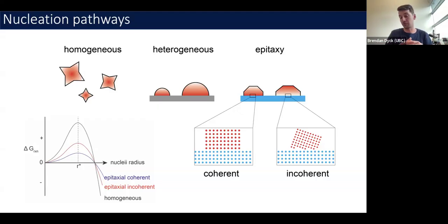And eventually we get to a critical radius or a size where we are now making enough of our more stable new phase that the free energy of making the new phase overwhelms the deleterious energy of making that new grain boundary. So homogeneous nucleation has this large barrier energy, right? And the actual magnitude of that ranges from approximately 10 kilojoules per mole for a mineral like quartz, up to as much as 500 kilojoules per mole for quartzite, where it's been looked at for the devitrification of a quartzite glass. So that's a very large energy penalty.